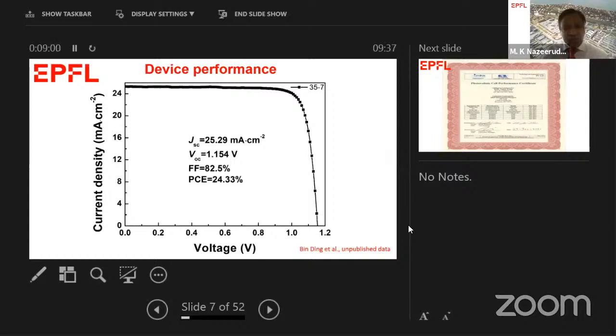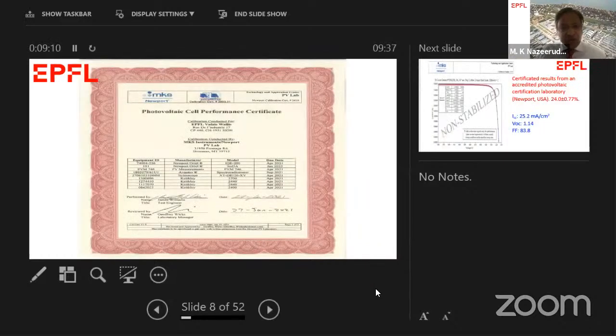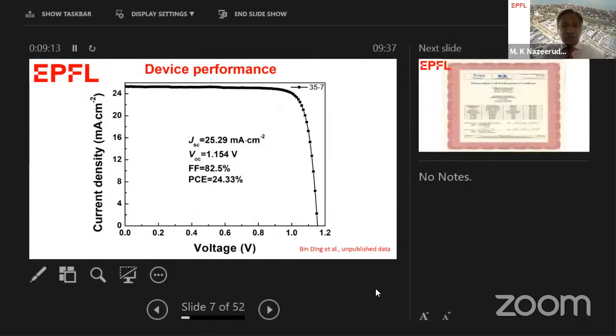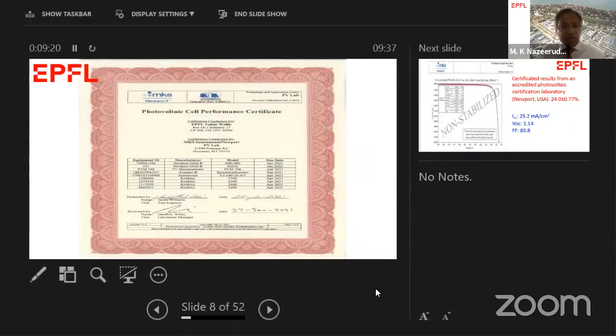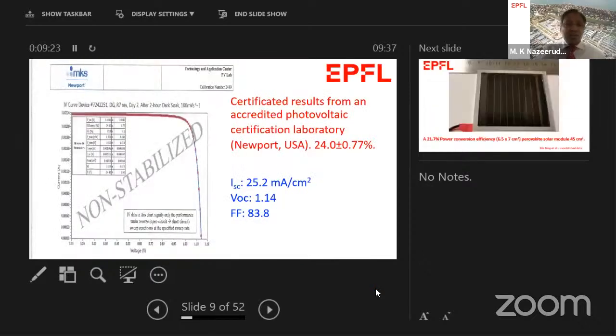Once we measure in the lab, we have to make sure that the data is certified in outside labs. So we sent it to Newport, and there they measured our solar cells on 27th of January. Yes, here you can see the solar cells measured at Newport. The short circuit current measured in our lab is very consistent with that measured at Newport, and the power conversion efficiency is comparable to the solar cell measured in our lab. So finally, we do have a 24 plus or minus 0.7% certified power conversion efficiency.